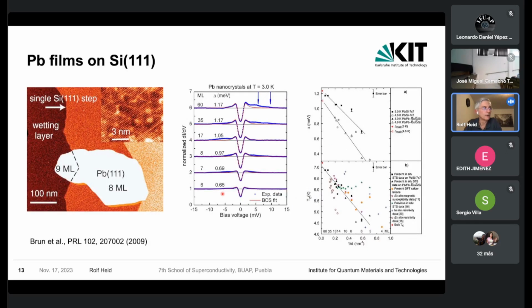Now I come back to the films. Now, why have these lead films been so interesting? For many years, experimentalists have been able to grow very thin lead films with a relatively large lateral extent. You see here a picture from STM, which shows that there are lead islands grown on the silicon 111 surface, which extend to several nanometers wide, but they are very thin, namely only 8 monolayers thin in this case.